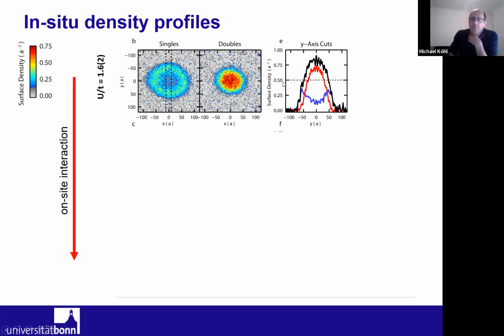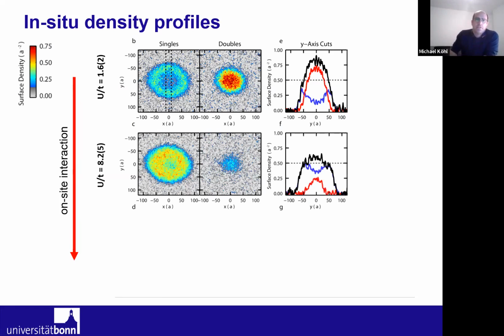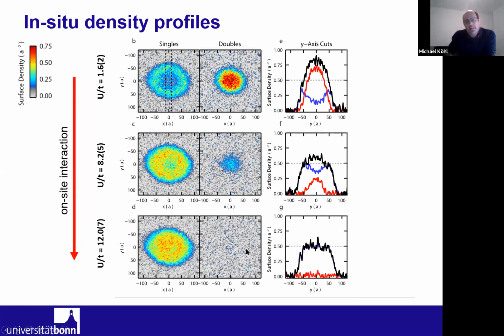And then we can take density profiles through these clouds, and then you see here in red is the doubles density, in blue is the singles density. We can just add them, and this then accounts for the total density distribution. And you see directly here the density reflects the shape of the harmonic trap, which immediately signals that we have a compressible metallic state. Now, if we increase the repulsive interactions, so this was a ratio of repulsive energy to kinetic energy of 1.6. If we now go to 8, then you see that we get many, many more singly occupied lattice sites, and the doubles slowly fade away. And at U over T equals 12, we only have singly occupied lattice sites, and the doubles have all gone. And you see also that the density is now flat in the center of the trap, which signals that we have an incompressible phase, and that is the Mott insulator. So from our density pictures, we can directly see this crossover very, very clearly.